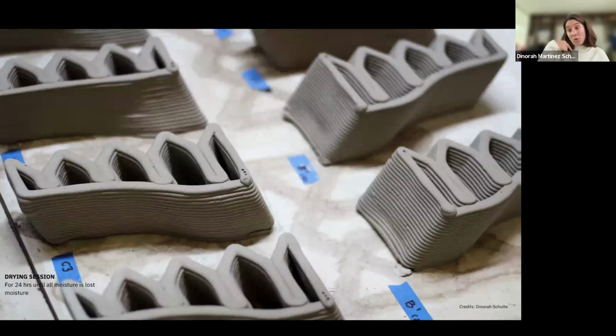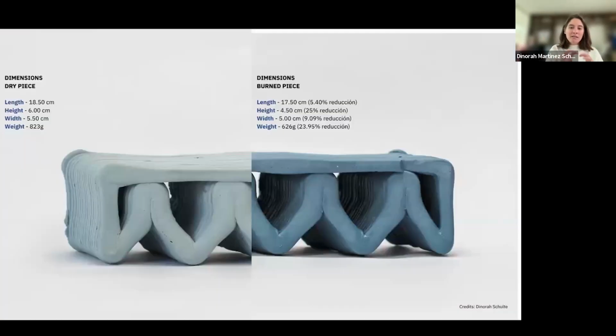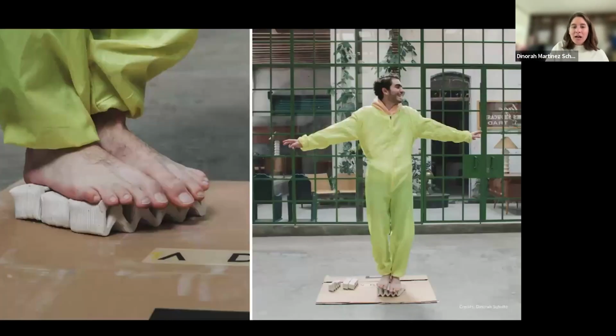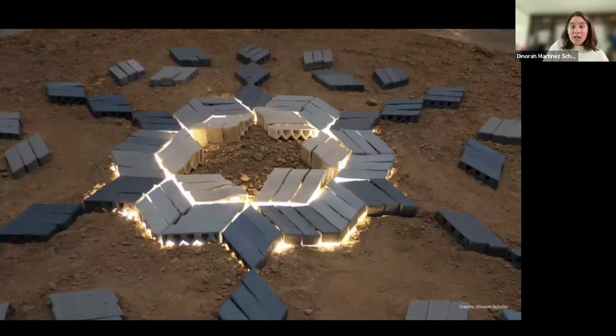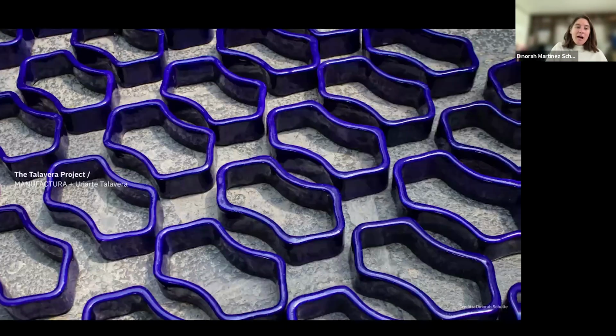So when we printed, this is how it looks. It looks a little bit gray, but it's very blue. So we left it to dry for 24 hours. And this is a picture that I really love, because you can see how the bricks look before the firing and then after the firing. We have to be very careful with the quantity of pigment that we add to the ceramics. And they also tested it physically to see if the floor system totally works. And this is the final project.